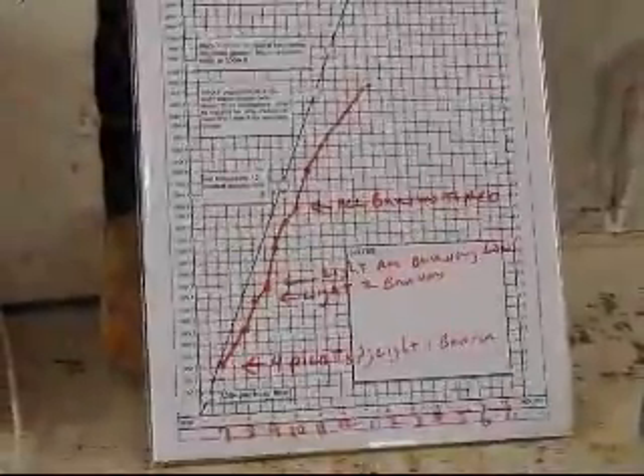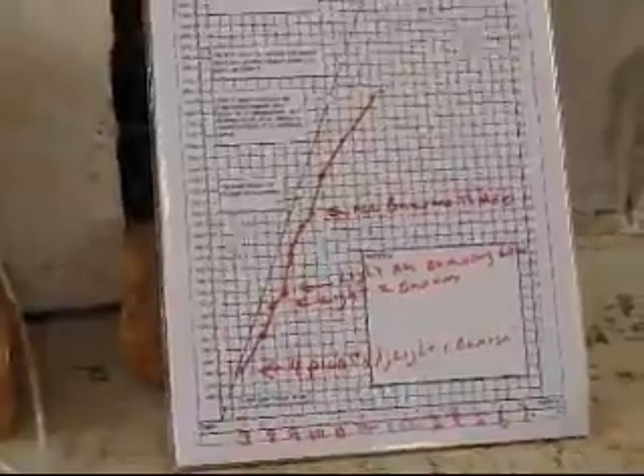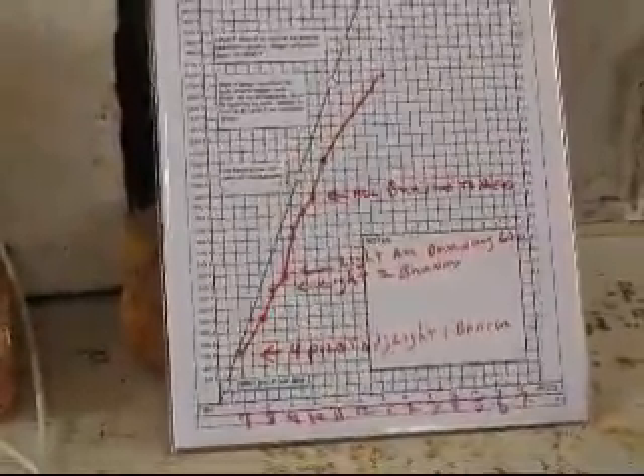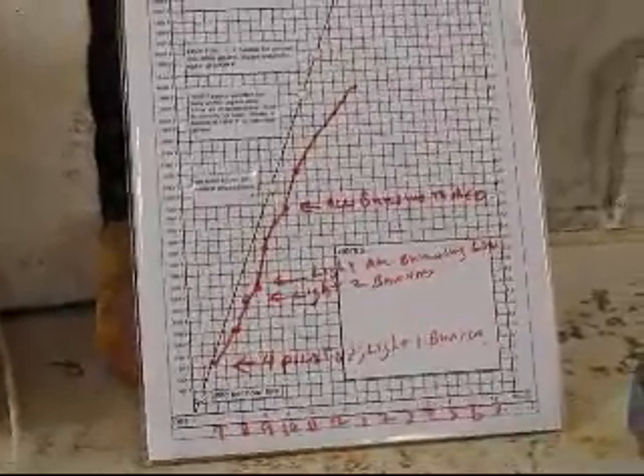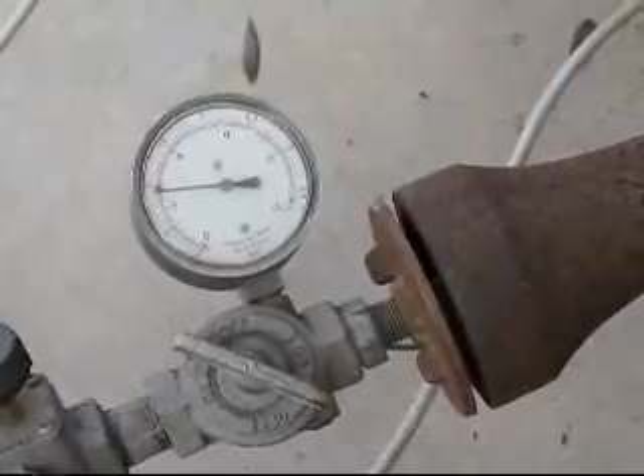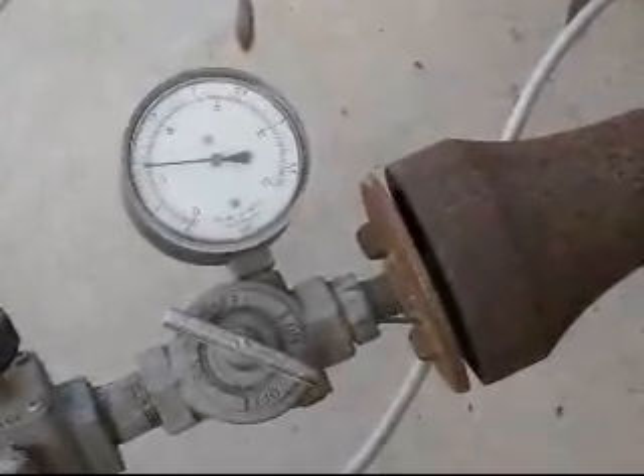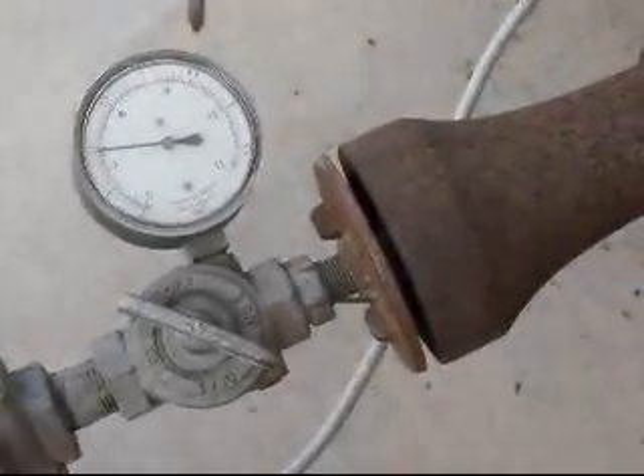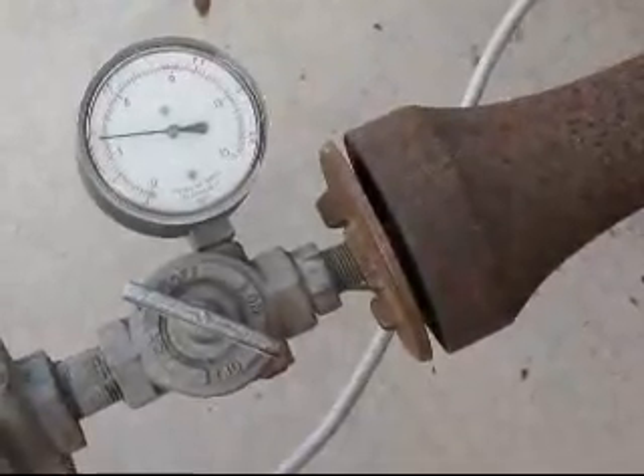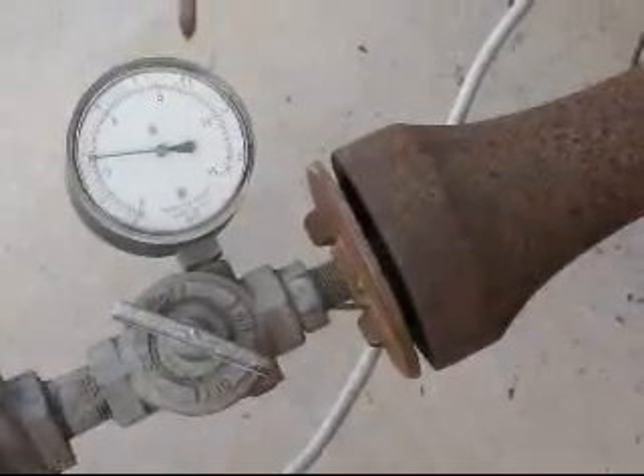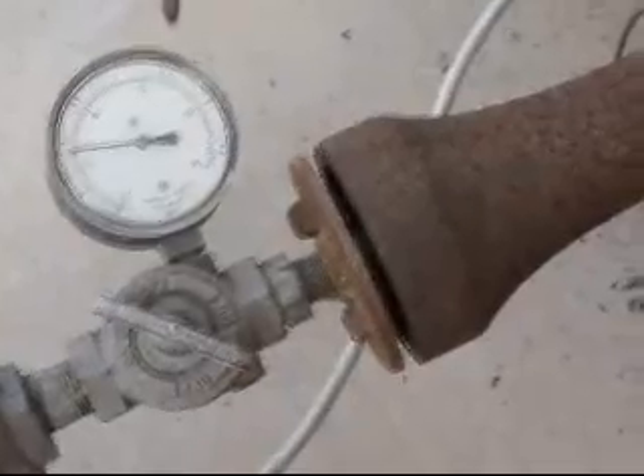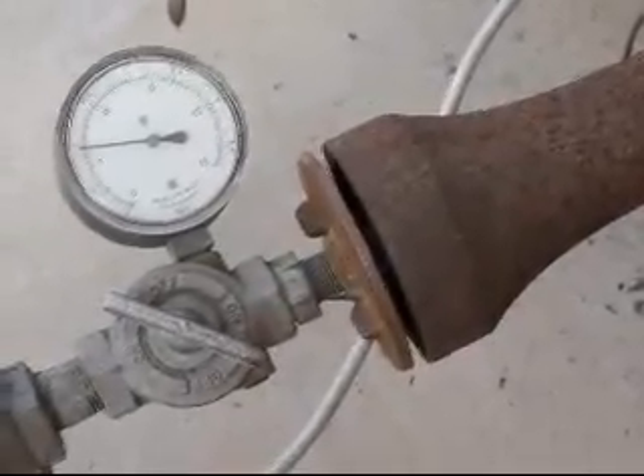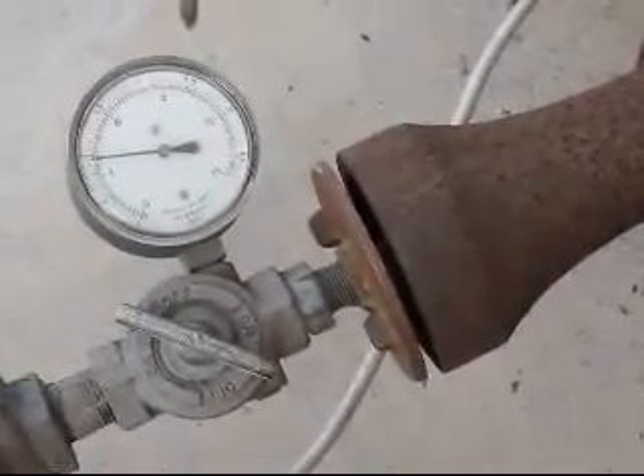Now 2 o'clock, the kiln has been climbing at just under 300 degrees an hour, and it's now about 1620, and it's time to start reduction. In order to set the kiln in reduction, the first thing I did was to slightly close the primary air valve. Then I turned the gas up to a reading of 4. And now I'm going to watch the oxyprobe and see how much I need to close the damper.